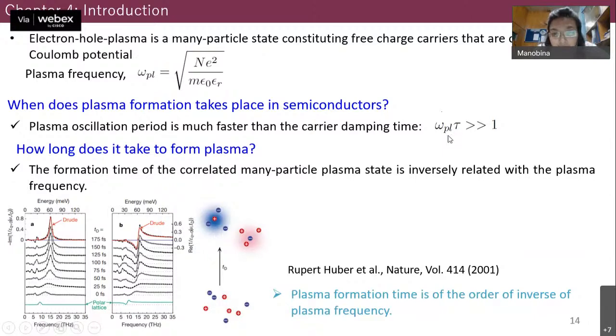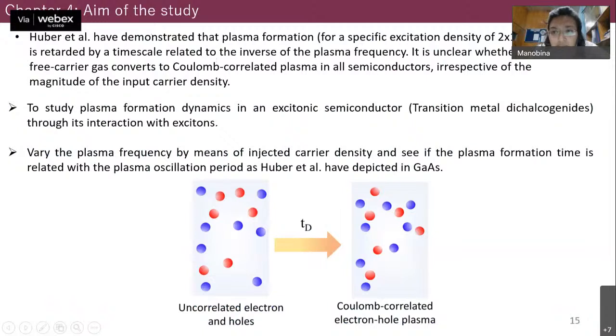So basically this plasma oscillation period has to be much shorter compared to any damping time in the system. Otherwise this plasma cannot sustain in the system. So in 2001, Huber and their group have shown that this plasma formation time in a semiconductor is of the order of the inverse of the plasma frequency. Now this study was performed in gallium arsenide and at a particular excitation density. So now what we want to do is change the excitation density and see whether this follows. So we are basically tuning the plasma frequency and want to understand the plasma formation time.